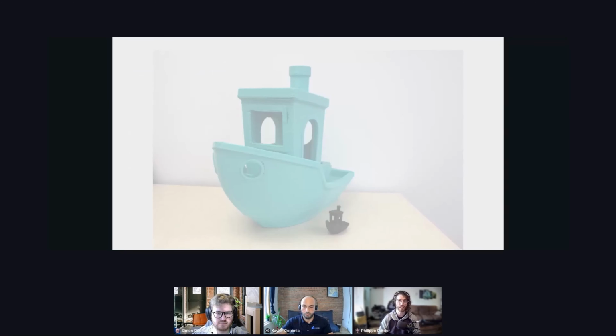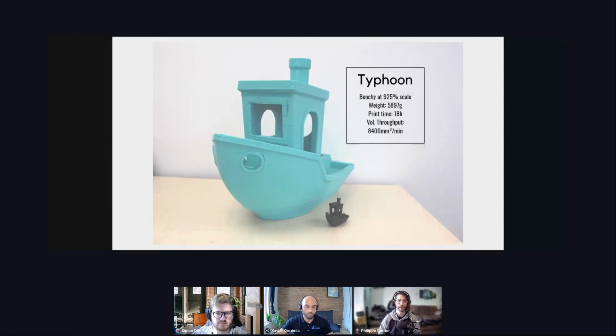Here's the widely common print test we did, a benchy at 925% scale. The big benchy took only 18 hours to print. Printing such a part with a regular extruder, considering 200 microns layer and 70 millimeter per second printing speed, would have taken more than 120 hours, which is 5 days, about 7 times longer than with a Typhoon, for a print that ends up being only half the weight.